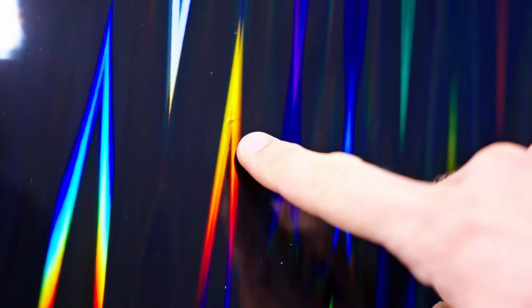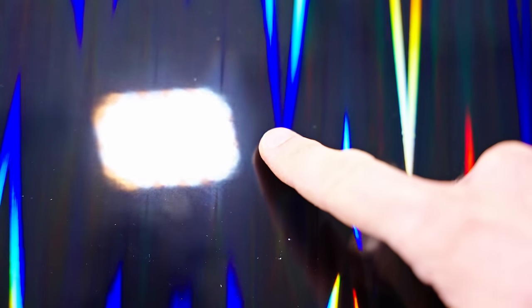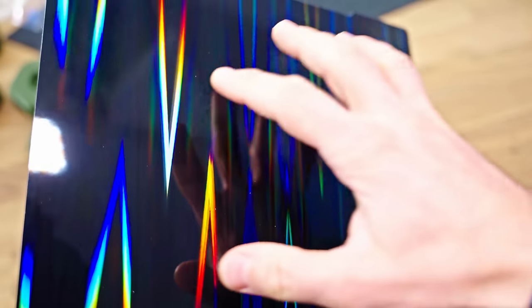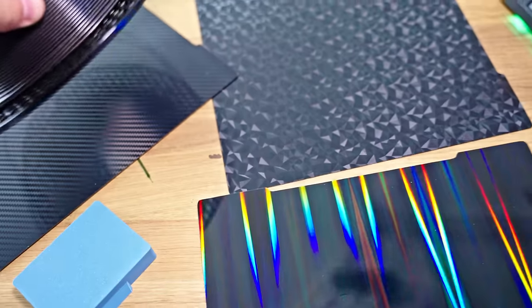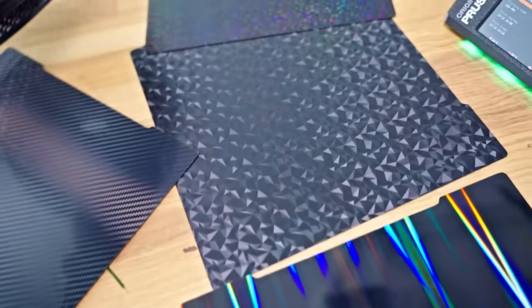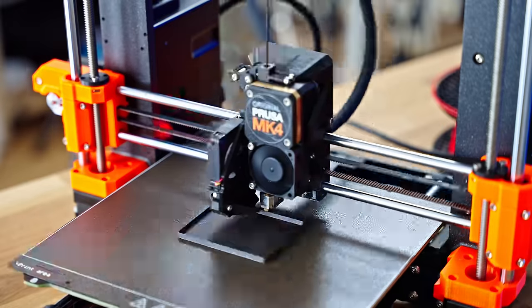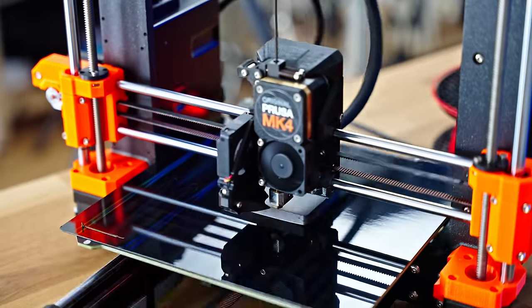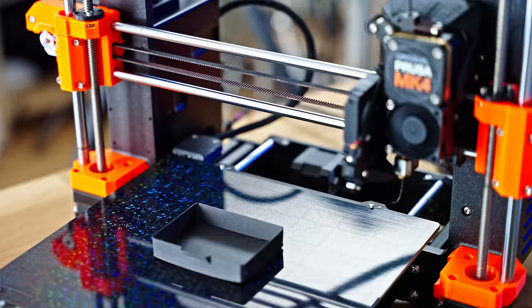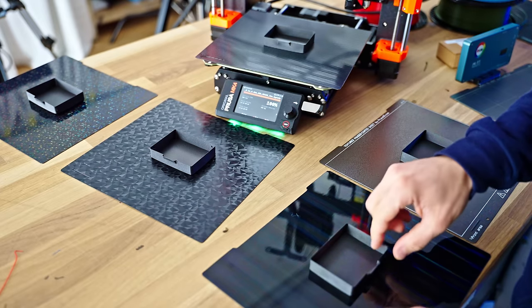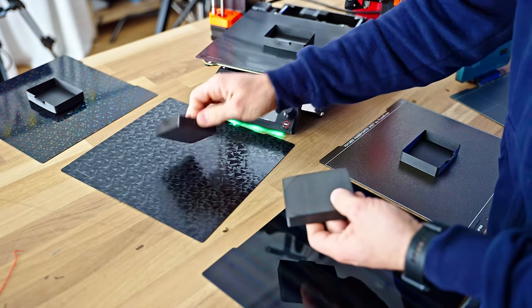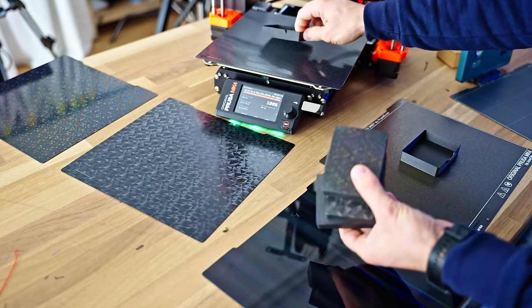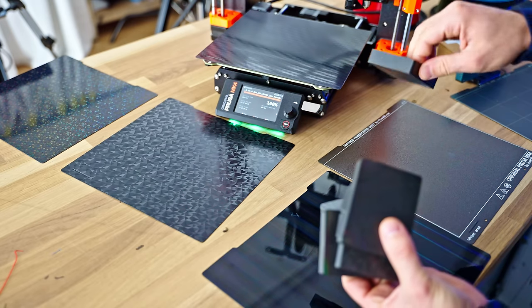And then on the H1H surface, this is so hard to see, I guess you can sort of make it out there. We are starting to see some peeling, and I guess this is going to imprint into your parts as well. It's just where the adhesive is starting to let go between the holographic film and the metal sheet. Alright, let's get some ASA printing and then we can get to a conclusion. Okay, so realistically none of these surfaces really stuck down all too well except for the textured PEI. That one came out pretty good.